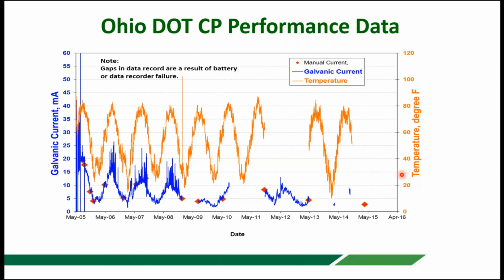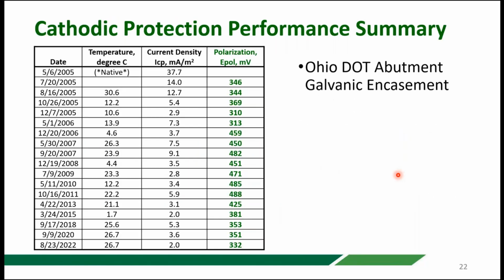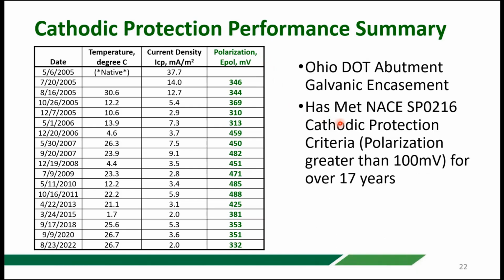steel. And probably more important than all of this is that they have been monitoring since 2005 a parameter called polarization, which is the main thing that you measure when you want to determine if a cathodic protection system is working or not. And the NACE, or National Association of Corrosion Engineers, standard for cathodic protection is that the polarization needs to be 100 millivolts or greater. And if it is, then you can sleep easily knowing that the steel is cathodically protected and not corroding. And the polarization for this structure has been well over 100 millivolts from 2005 up to over 17 years, and continues to function.